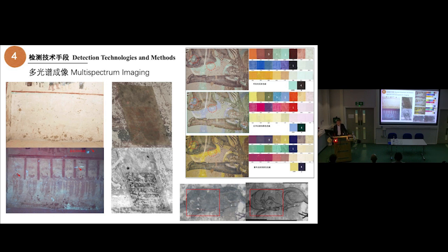And here we find some stamp. This is the mural stamp. So we also developed a systematic method: using a multispectral image, we can determine what kind of pigment. We can use this method to determine most of the pigments and the organic colors. Because this is not in the normal light, this is IR light. We can find this. The normal light is green. The IR and this green, and the UV light is yellow. So we combine these different colors, and we can determine what kinds of pigment.